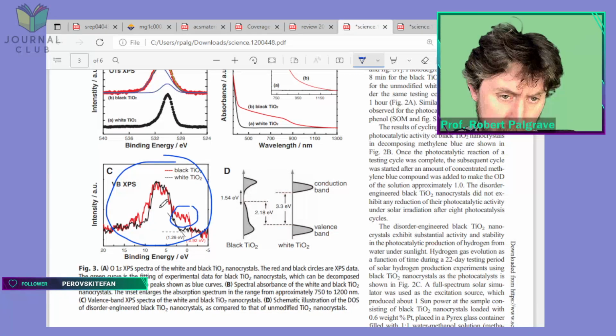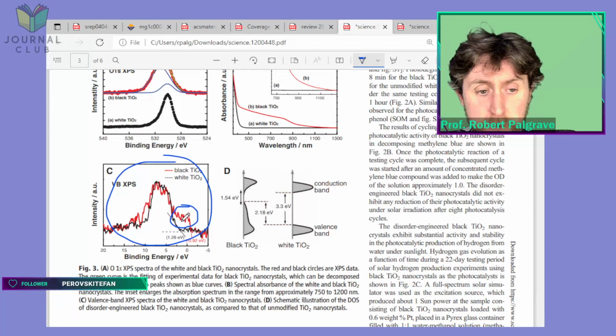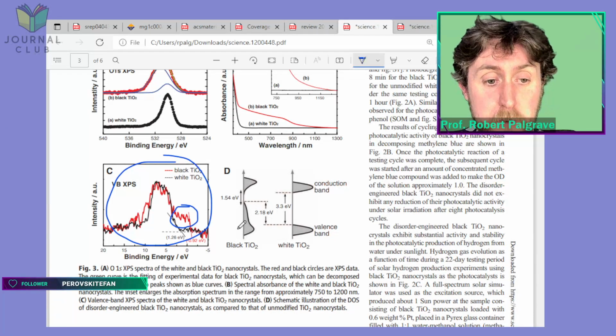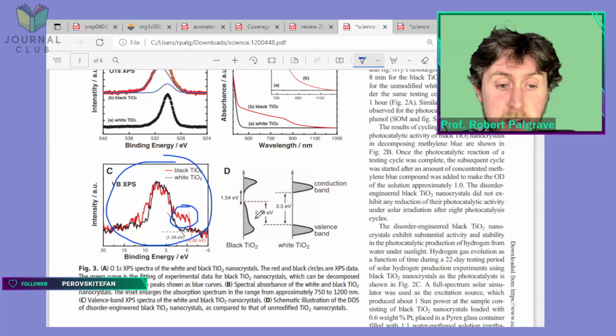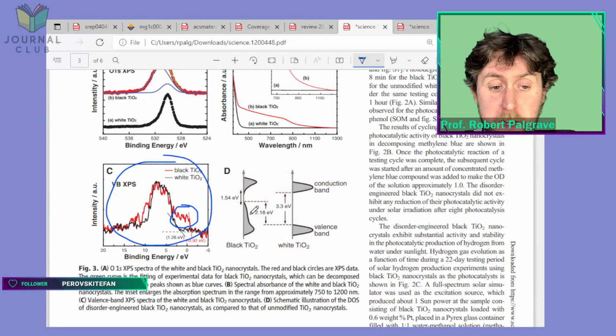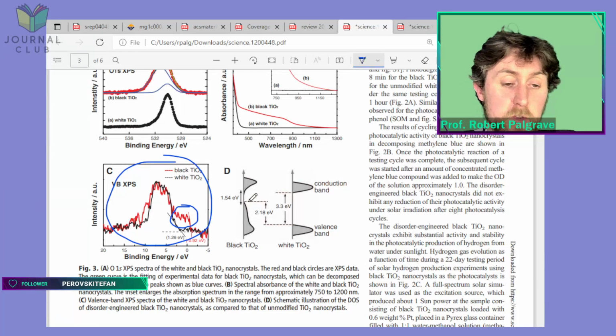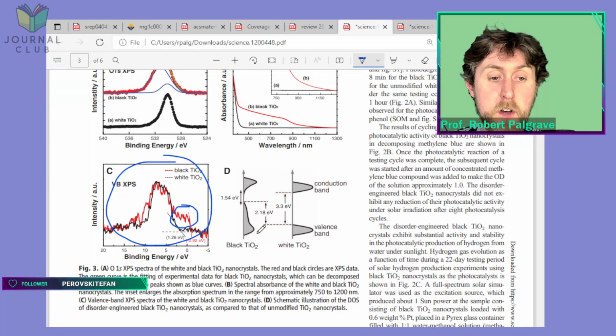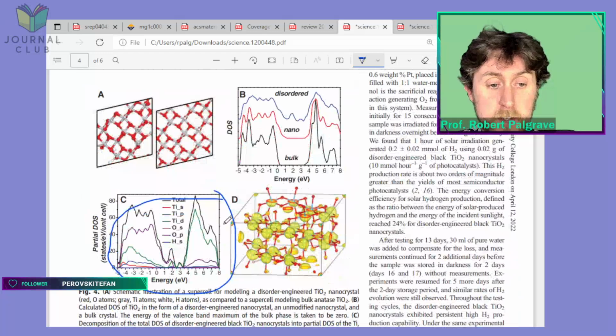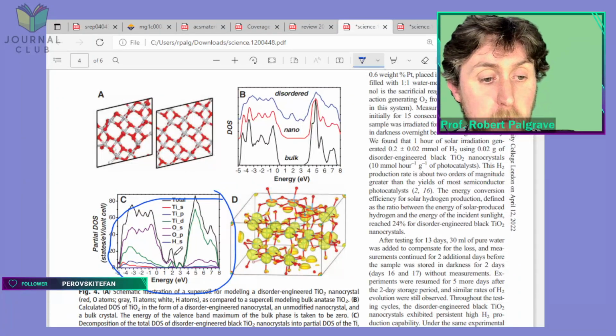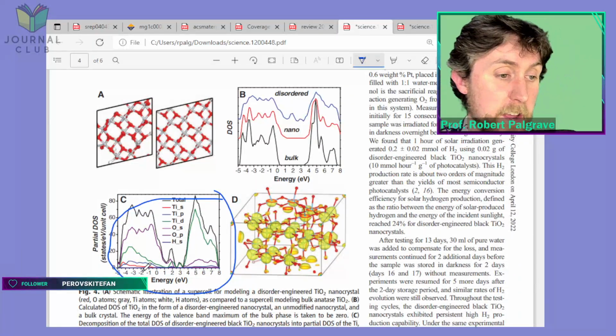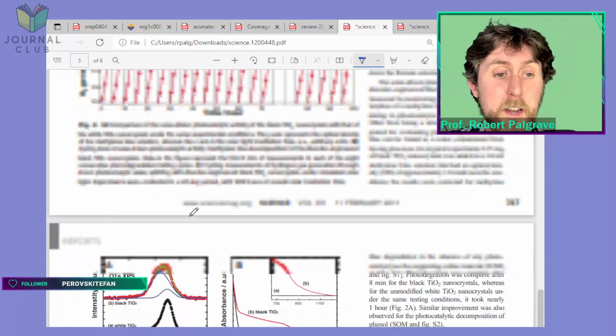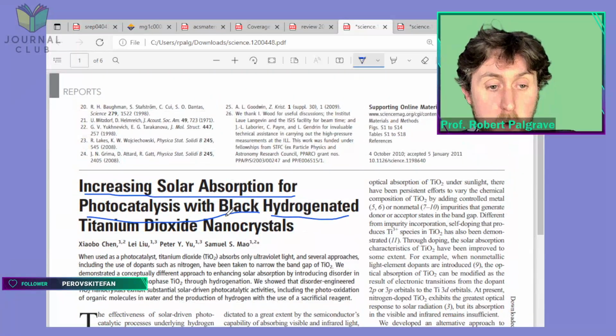So experimentally you can see a difference in this spectrum, and they interpret it with this cartoon as a change in the distribution of the outermost electrons in the valence band region of this material, which kind of makes sense, and it ties in with their DFT calculations as well. So that's a little bit of the background. This is the origin story, I guess, of black hydrogenated titanium dioxide nanocrystals.